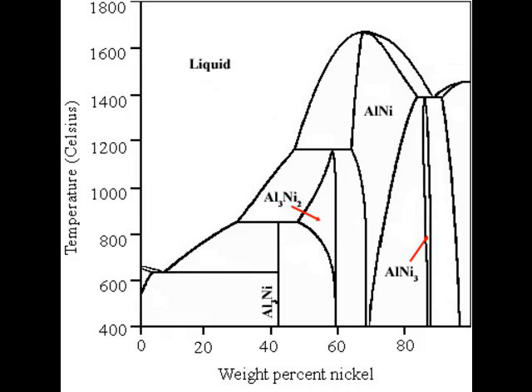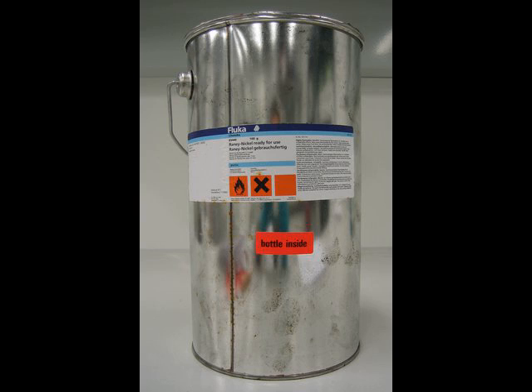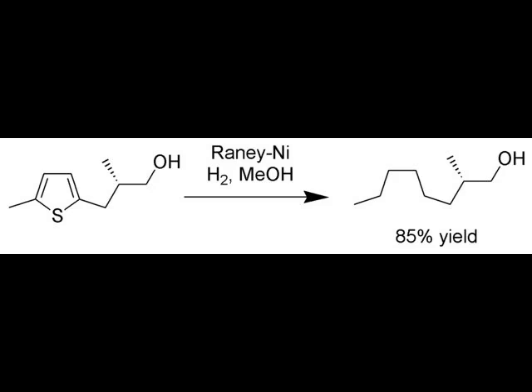Section 1: Preparation. Alloys are prepared commercially by melting the active metal — nickel in this case, but iron and copper Raney-type catalysts can be prepared as well — and aluminum in a crucible and quenching the resultant metal, which is then crushed into a fine powder. This powder may be screened for a specific particle size range depending on the application. The initial alloy composition is important because the quenching process produces a number of different NiAl phases that have different leaching properties, which may result in markedly different porosities in the end product.